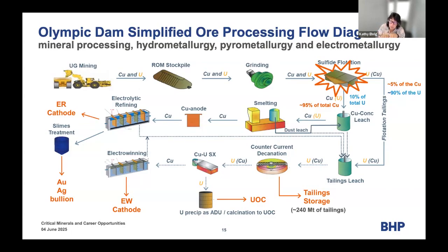The copper concentrate goes through a leaching process. There is a little bit of uranium in that. That leaching liquor goes back into tails leach. That copper concentrate goes into a flash smelter. We make an anode from that. That anode goes into electro refinery, where we're recovering our gold and silver from, and eventually into the slime side.